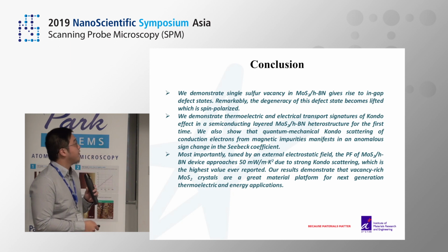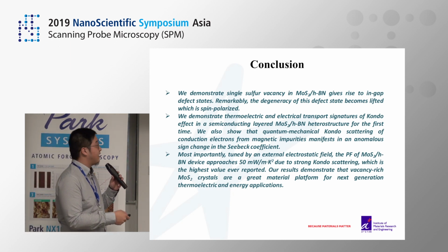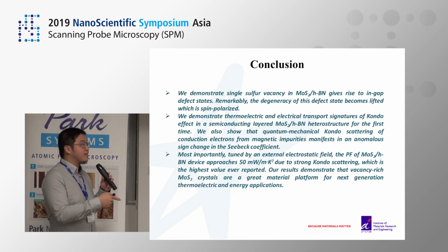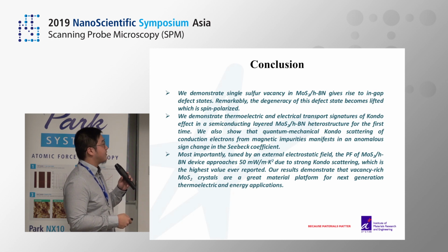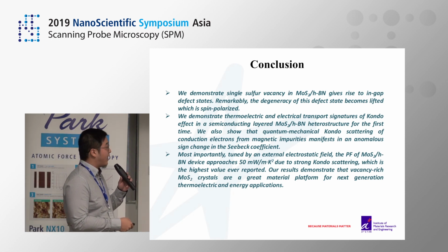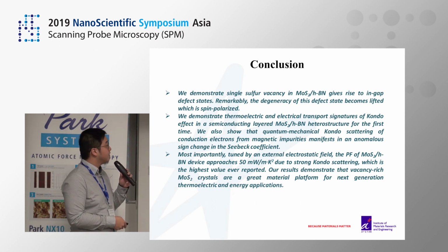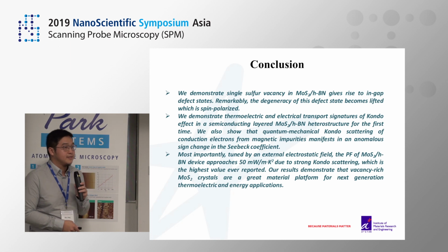We have a quick summary. We demonstrate that vacancies in MoS2 can give you strong local magnetism. And we also demonstrate that this strong scattering due to the magnetic effect can give you the sign change in the Seebeck. And due to this strong scattering, we have a large enhancement in the thermoelectric transport performance. That's all. Thank you.